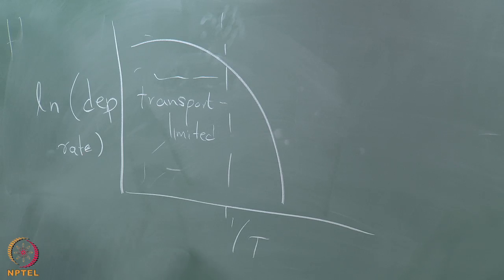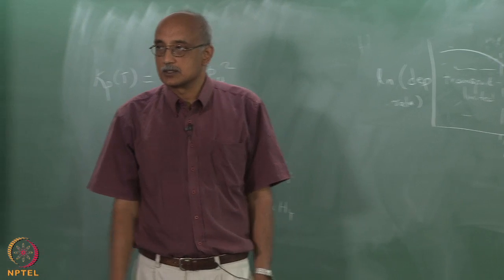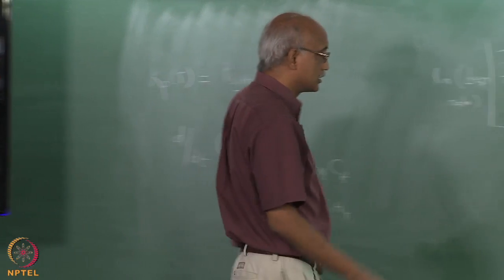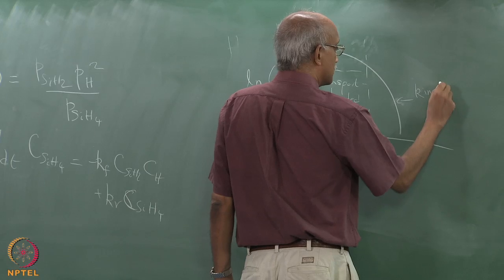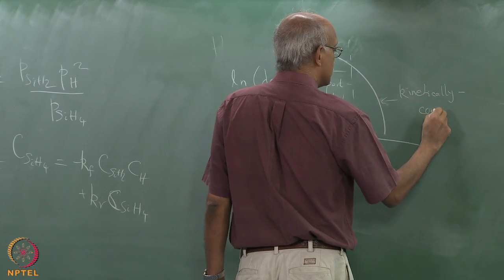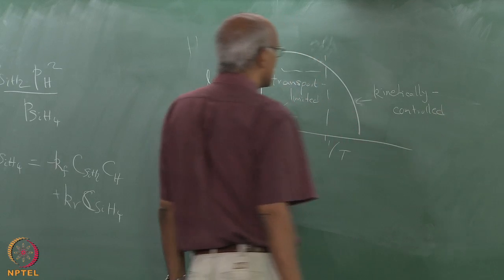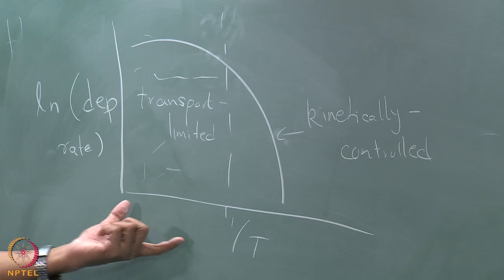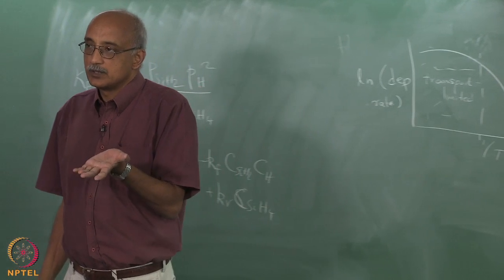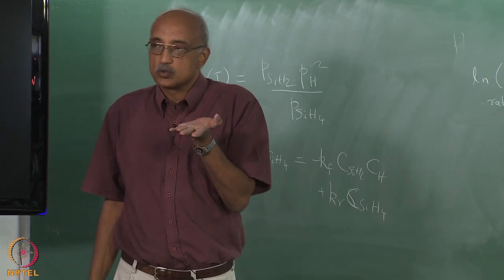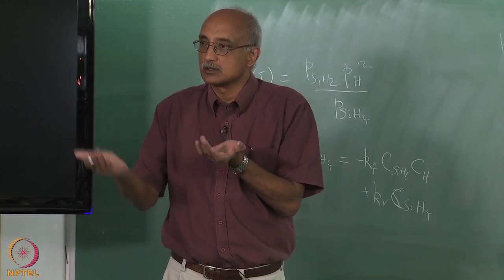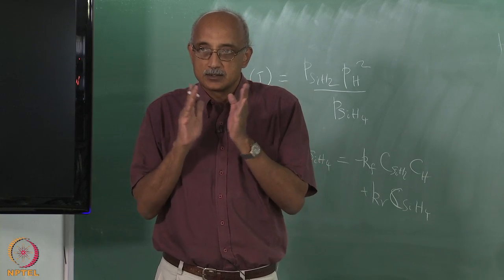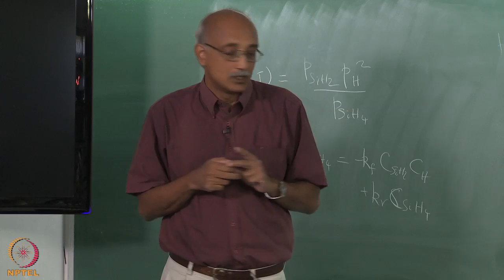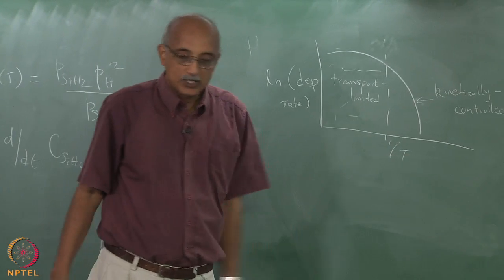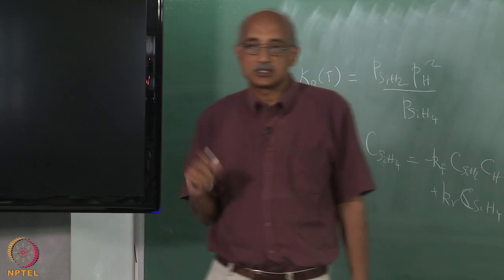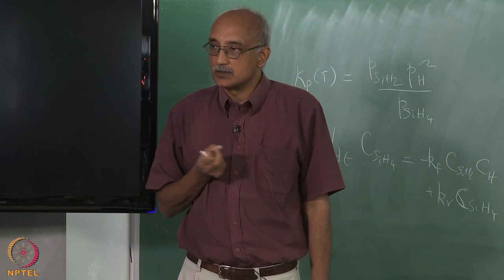And of course, by extension then, the region where you see a very sensitive dependence of the rate of deposition to surface temperature, you would call this a kinetically controlled regime. Another way to state it is, this is the region of very low temperature, right? So as you increase the substrate temperature, eventually it gets to be so high that there is no kinetic limitation. The reaction will proceed as long as the reactants are delivered to the reacting surface. Whereas, in this limit, the temperatures are low enough that even small variations in temperature can have very significant influences on the rate of deposition.